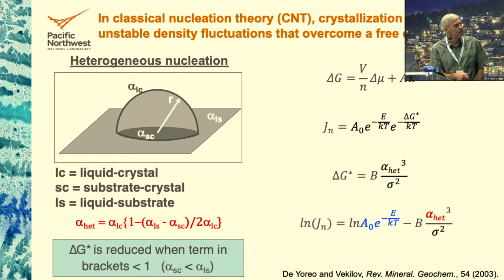But now there are three interfaces. There's an interface between the particle and the solution, and that's the one that we had in the case of a particle in bulk solution. There's also a new interface between the particle you're forming and the substrate. And then there's an interface that got covered up. And you have to take that into account too, right? Because if you look at the change in free energy, you've hidden that piece of the surface, and so you've changed the free energy just for that reason. So the net interfacial free energy contains all three of these terms. And this term, alpha heterogeneous, is going to be smaller than alpha liquid crystal as long as this term in the brackets is less than 1.